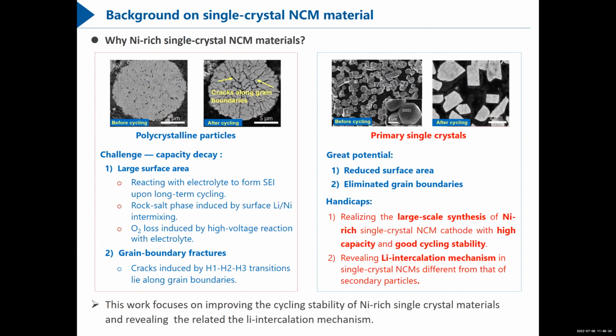There are many reasons for the capacity degradation of nickel-rich materials, but most of them are related to particle morphology. Normally, the commercialized nickel-rich NCM material has polycrystalline particles, right? But this kind of morphology always has a large surface area. The large surface area means there will be large contact with the electrolyte, okay? As a result, there will be more surface side reactions, and finally grain boundary fractures, and this is the main reason for capacity decay in NCM.